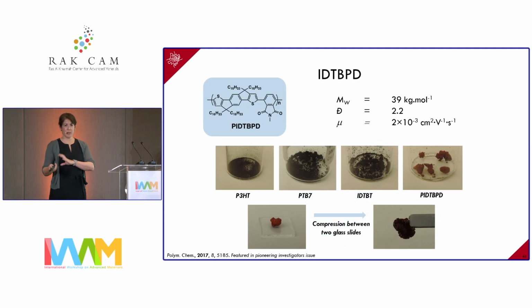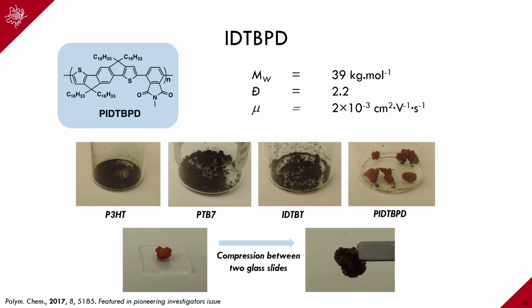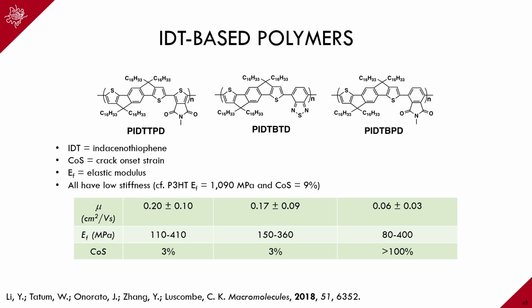So semiconducting polymers, being designed to be more crystalline than amorphous, tend to be very brittle. And usually what we isolate because of that brittleness are powders. Like, you filter them and it just kind of falls apart into hard powders. But that one polymer that we made was actually very squishy. It had a completely different texture. And that made us look at the mechanical properties of these materials. And what was intriguing about these mechanical properties was the following.